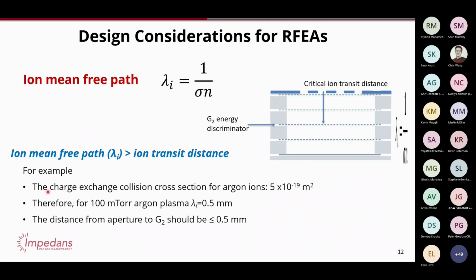So here's an example. This is a charge exchange collision cross section. What that means is an argon ion, let's say, hitting an argon neutral, and then they can exchange the charge. This has a really, really large cross section compared to others. This is kind of a worst case scenario, really. So say if you want to take a measurement in a 100 millitorr plasma, that mean free path works out to be about 0.5 millimeter. So that means that this distance here would have to be less than 0.5 millimeter in order to get a good measurement at 100 millitorr. These are the kind of things you have to think about. And this is also suggesting that these sensors would be limited in pressure range, because once you go above a certain number, the sensor gets too small to work with.